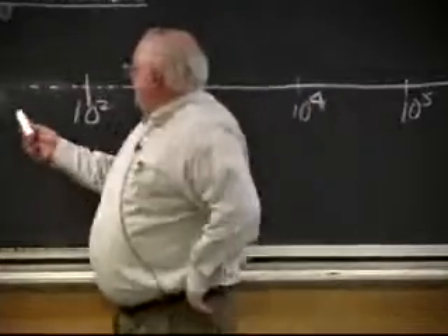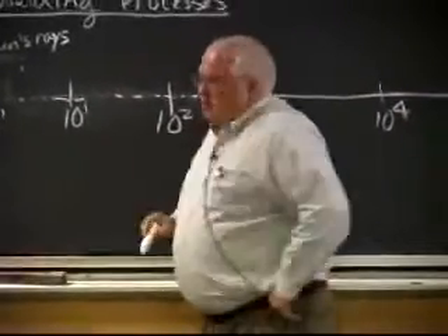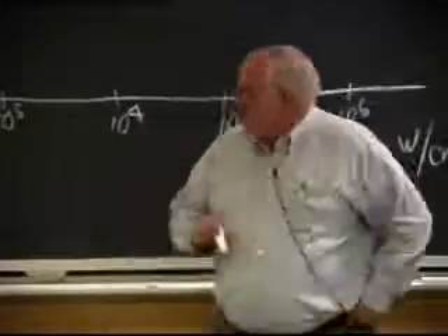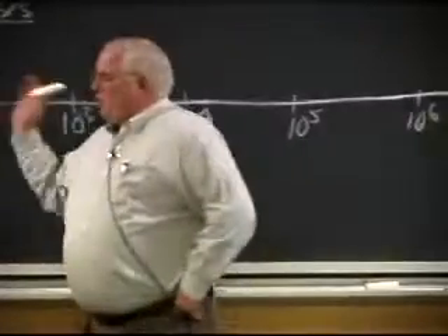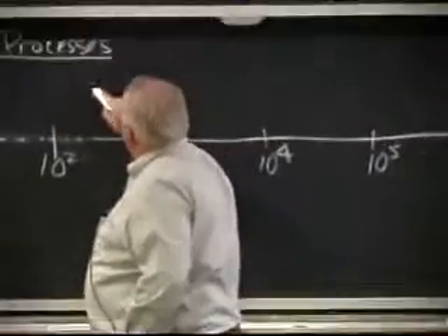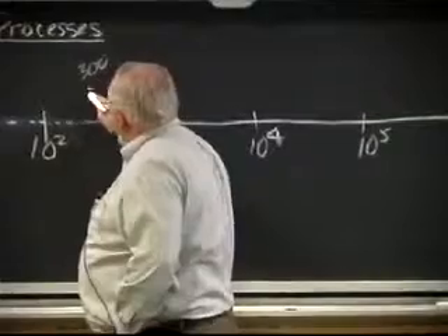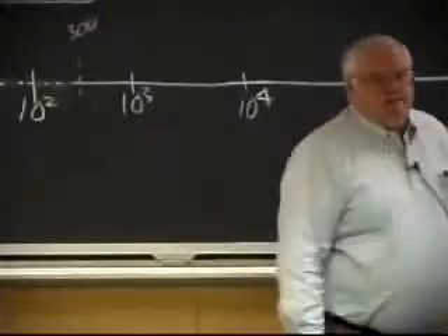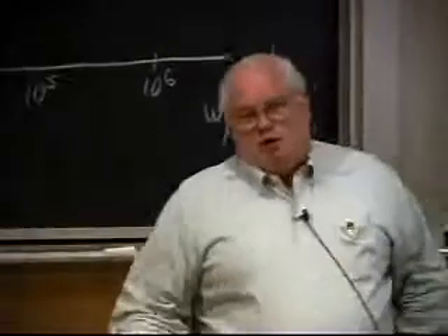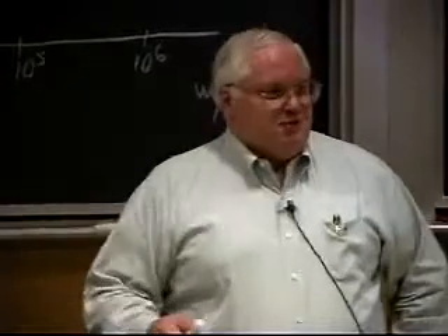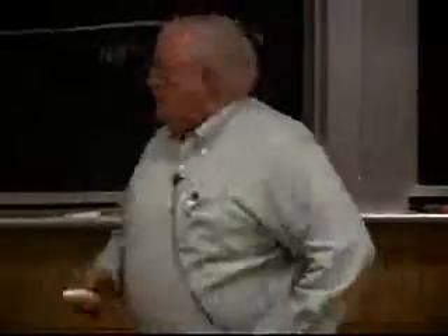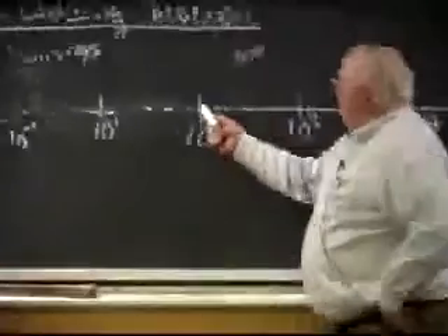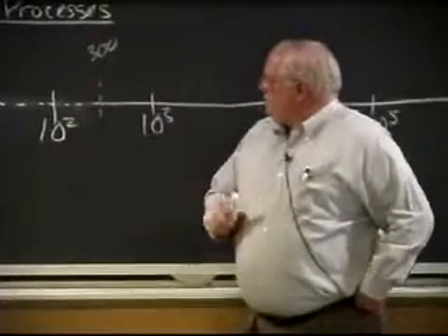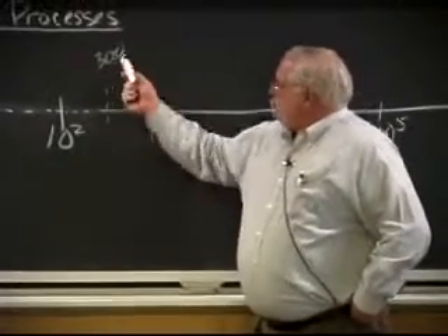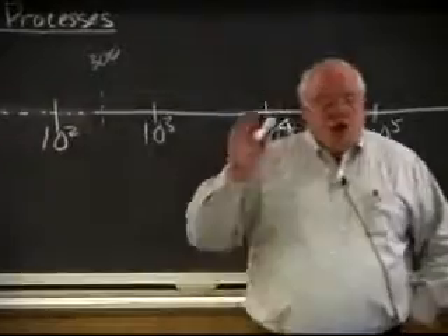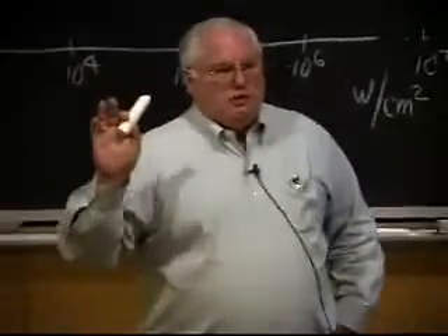Anyway, it turns out that if I'm interested in heating the surface of metals, I have two limits. Below about 300 watts per square centimeter, and on a log scale, 300 is halfway in between, since 3 times 3 is approximately 10, half a decade is roughly 300. At about 300 watts per square centimeter, or below that, you can't melt the surface of the metal.